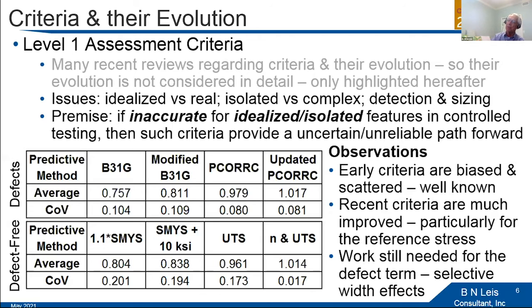So if we look historically at predictive methods, and the upper box here focuses on defects, you'll see there that we've got a comparison of some early criteria, B31G and modified B31G, versus some more recent criteria, PCORRC and a more recent version of PCORRC. And the big difference here is evident. There's significant bias present in these predictions. That bias tends to be removed and the scatter reduced by the modern criteria. So there's a big step between the early and the modern. But if you compare a lot of the modern criteria, they don't discriminate very much differently. They all have their roots in plasticity theory, or generally have their roots in plasticity theory, and as a consequence of that, have more or less comparable errors.